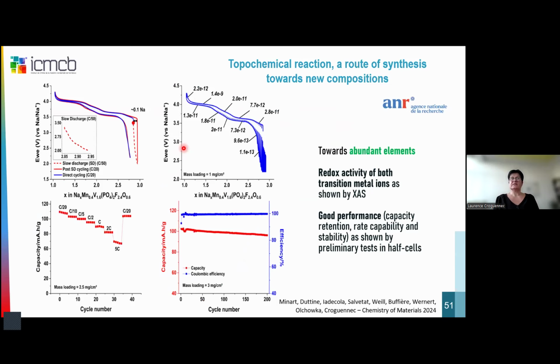And interestingly, these materials behave very well. You can see we have very small polarization, very good reversibility. We have activity of vanadium and manganese in these materials, so it means no loss of capacity versus the vanadium-only materials. Very good behavior at high C rates and upon long-run cycling. Of course, these are preliminary tests in half cells, so it could be interesting to continue for better maturation.